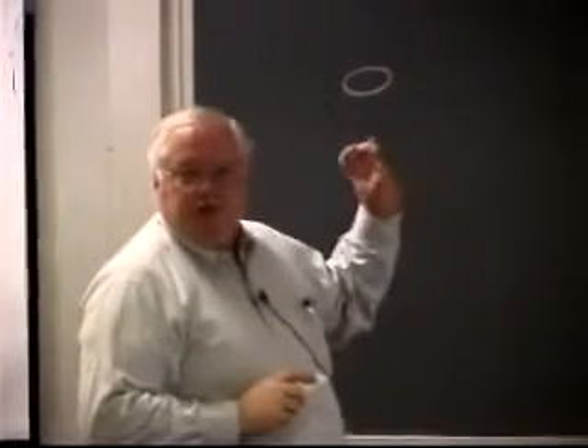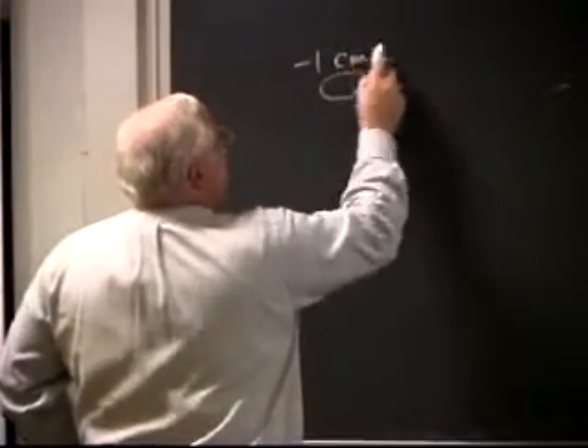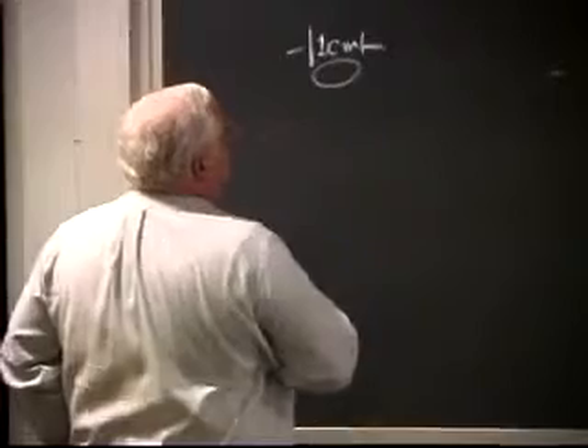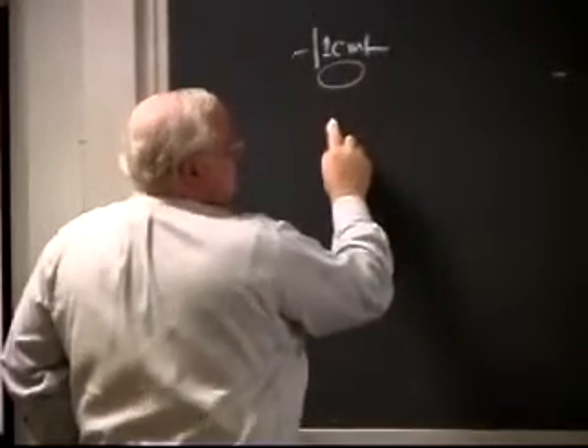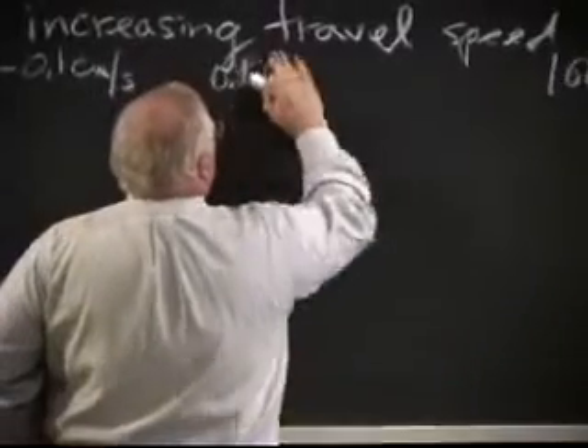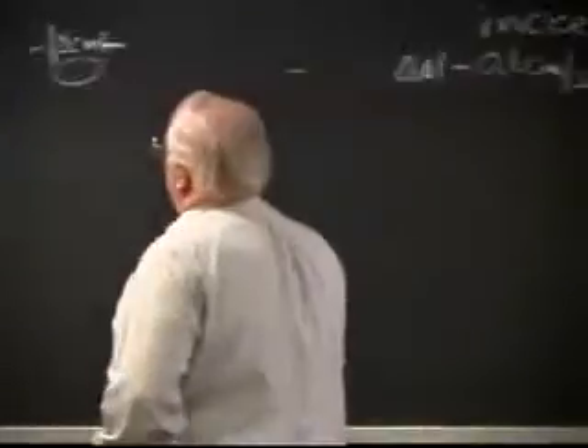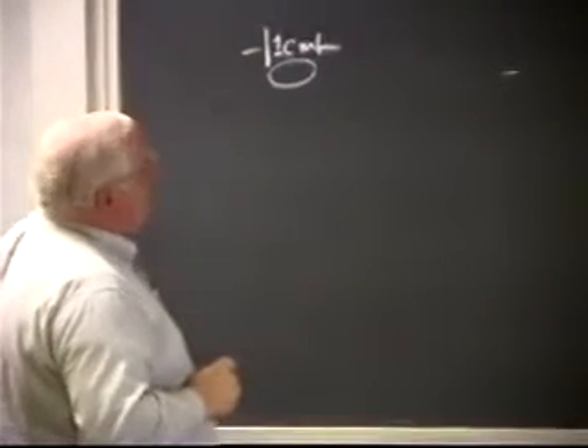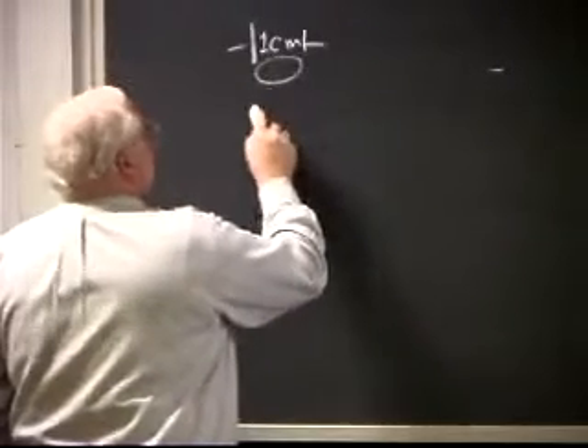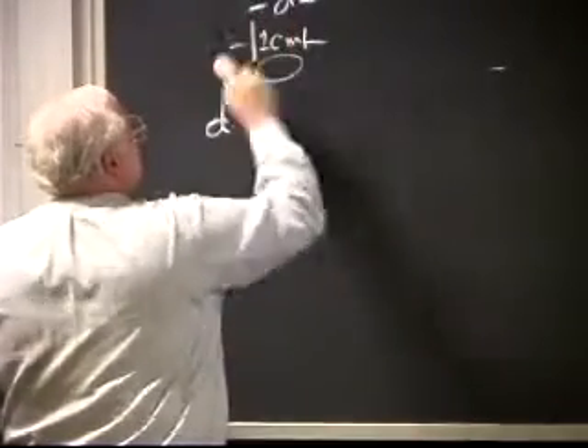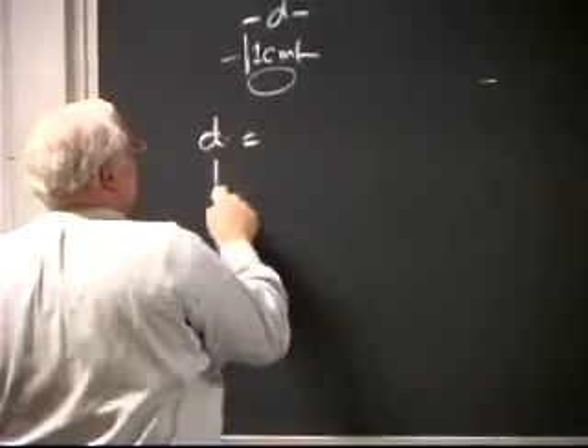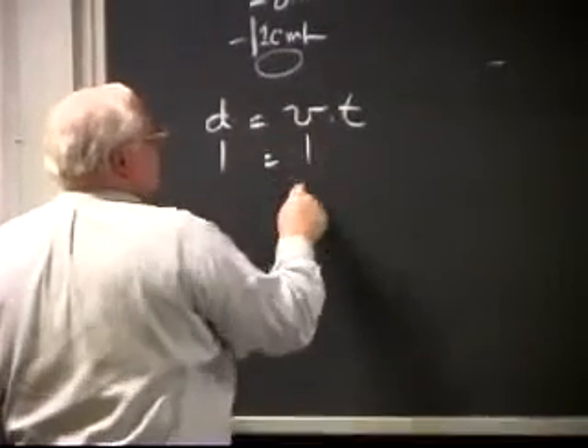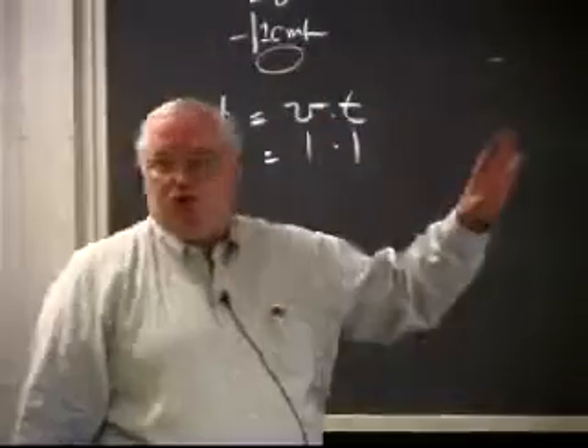Now, if I start thinking about this and I say, well, gee, let's say my weld pool is 1 centimeter in size, so it's 1 centimeter in length here. And I'm traveling at, that's supposed to be 0.1, that's supposed to be 1.0, I'm sorry, 0.1 to 1.0. And I'm traveling at a tenth of a centimeter per second. So I have a distance d, the diameter of the pool, is equal to, and that's 1, the velocity times the time. And if that's 1, then it takes 1 second to traverse that pool from one spot to another.